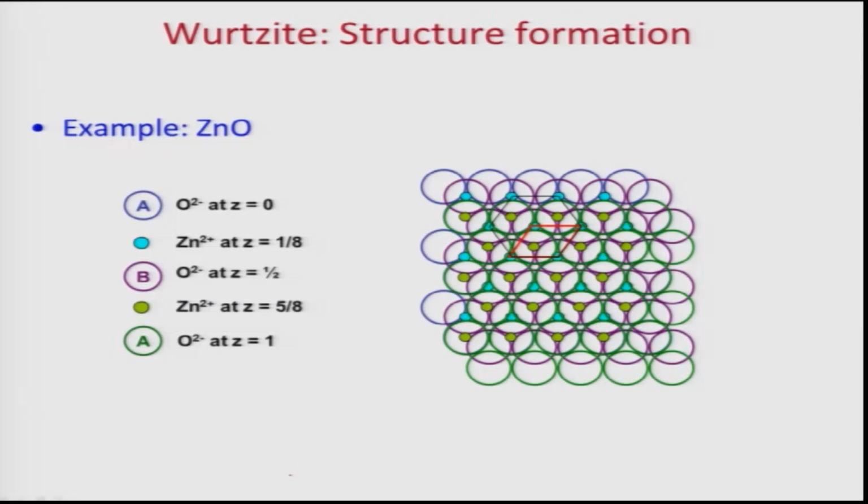So, this is the smaller unit cell with 4 of these light blue atoms which are at the edges, and the one which is sitting in the middle is the tetrahedral atom. So, this is basically the way you can draw the hexagonal close packed wurtzite structure with tetrahedral sites filled up to 50%. The next structure in this category is corundum.